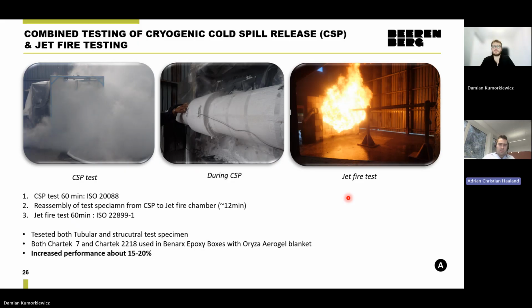Yet another test, a CSP and jet fire test. This was for the thick pipe specimen, so up to 40 millimeter. And we also do thin specimens. This was part of a test program for Chartek 2218. The goal of the test program was several factors, but one, to transition into a boric acid-free system, which is an HSE concern for some operators. Also to reduce costs by going into more efficient technologies, reducing thickness and complexity and cost of the system. And due to the thickness reduction and the higher distance between locks and bands tested there, we actually achieved almost 20% reduction in cost for the product just by transitioning Chartek technology.